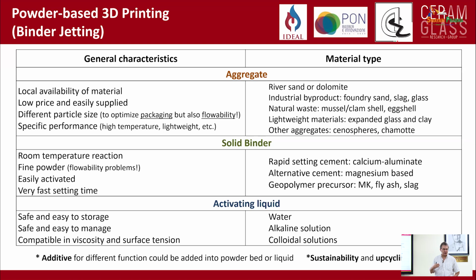But what we can do is to reduce the amount of metakaolin by adding fillers. And also the reason for doing that is that metakaolin deriving from the decomposition of clay is more expensive than, for instance, sand. So we mix different aggregates inside our powder bed, but we still have the problem that we cannot have a lot of metakaolin because otherwise the powder bed will not be flowable. But I will describe how we can solve this problem.